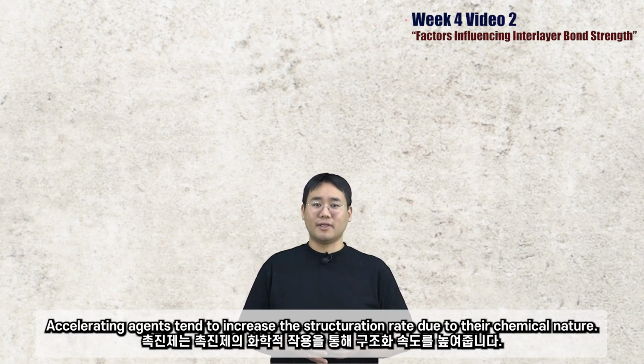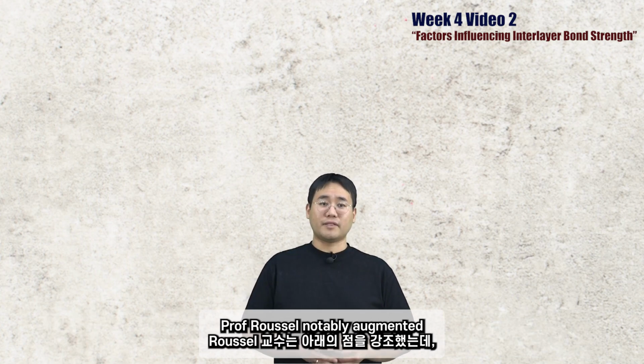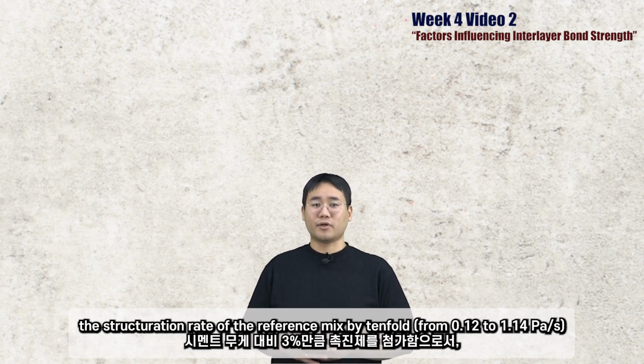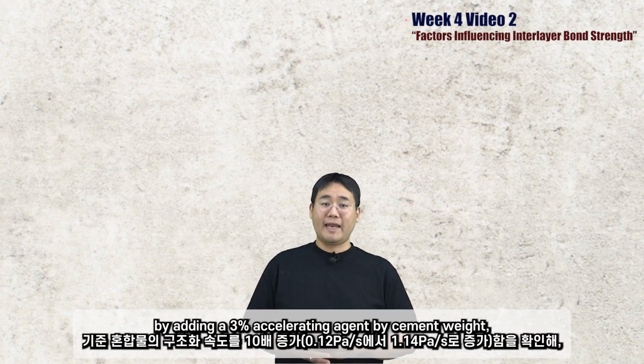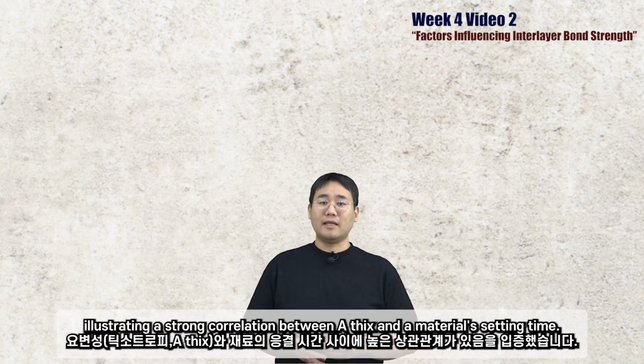Accelerating agents tend to increase the structuration rate due to their chemical nature. Professor Roussel notably augmented the structuration rate of the reference mix by 10-fold by adding a 3% accelerating agent by cement weight, illustrating a strong correlation between the accelerator and the material setting time.